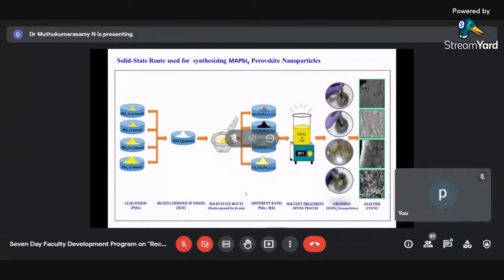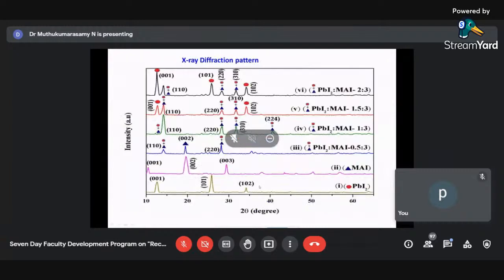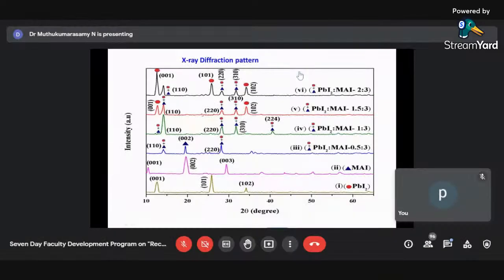And we have fabricated. Now, first we have prepared methylammonium lead iodide. You can see the process. We mixed it by using a grinder type of arrangement, then methylammonium iodide. So here one thing which I want to tell you is, when we change the amount of lead iodide, we were able to see either there was excess of lead iodide or excess of methylammonium iodide. So we were able to optimize, and for the 1:3 lead iodide to methylammonium iodide combination, we got only perovskite.